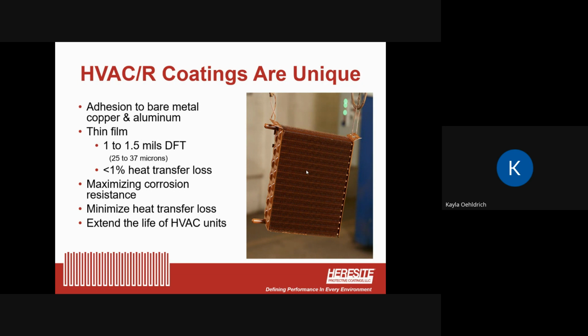So a typical paint is 4 to 7 mils. Let's say a primer and a 2-coat finish system. That's what most people that apply high-performance coatings are looking for. And we're only 1 to 1.5 mils. So if you were to take a conventional primer finish system and put it on that coil, it can drop as much as 80% in heat transfer. So these are really unique coatings, and they require some special testing.